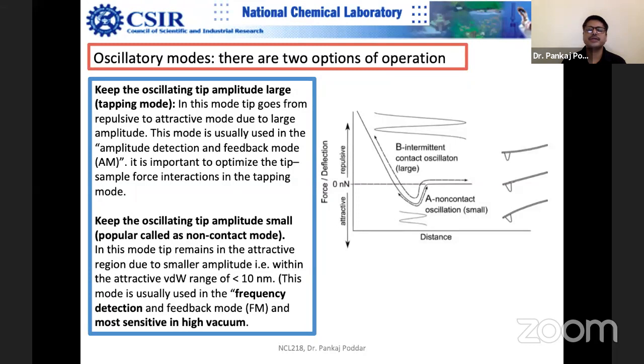because the problem is the water layer. The water layer is the enemy, because the tip is just hovering very close to the surface. The capillary forces of the water layer can grab the tip towards the surface. So this non-contact mode is not possible in ambient conditions. That is the reason this mode, which can give you atomic resolution and is highly sensitive, is normally done in high vacuum or ultra-high vacuum. There should not be any water vapor. This is a specialized mode, but it is really considered one of the best modes possible.